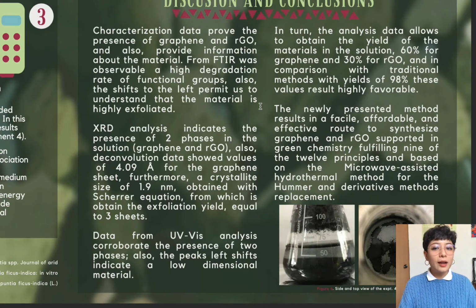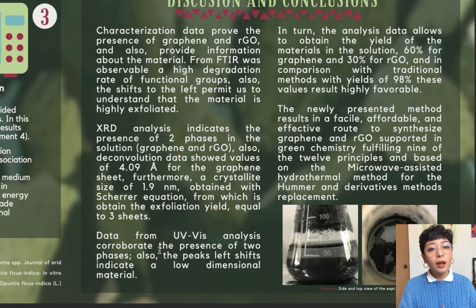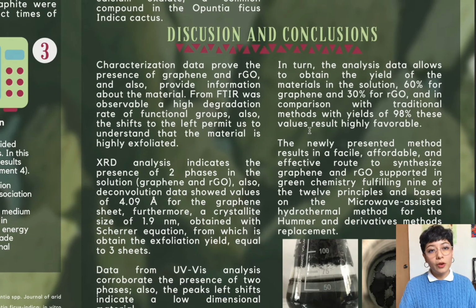Also, the deconvolution data showed values of 4.09 angstroms for the interlaminar distance of the graphene sheets. Furthermore, a crystallite size of 1.9 nanometers was obtained with the Scherrer equation. Moreover, from this last value, the exfoliation yield is obtained, which equals about 3 sheets. Data from ultraviolet visible analysis corroborate the presence of two phases. Also, the peak left shifts indicate a low-dimensional material.